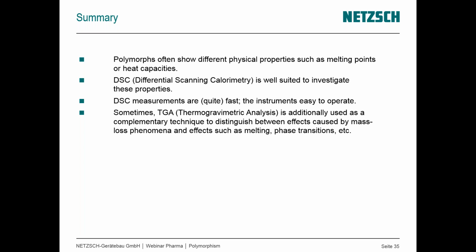So in summary, we looked at polymorphs. We looked at polymorphs via differential scanning calorimetry, and we used the thermophysical properties of these polymorphs, their thermal stability, the kinetics of cooling, to look at different forms. We saw that polymorphs can have different forms that are more or less thermodynamically stable, some forms which are metastable, so that we can have materials that are in general less stable that are converting into more stable compounds, some that go through transitions from stable to metastable and back through to separate forms before melting.